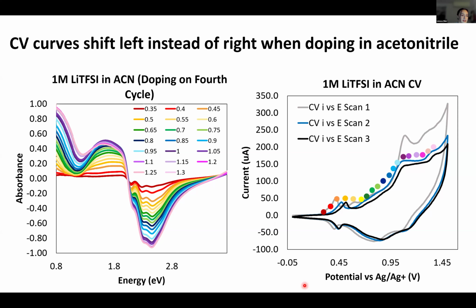And we hypothesize that this is due to regions getting irreversibly doped. They're not fully dedoped on the negative sweep. And so then the next cycles are doping the remaining undoped regions, which is getting harder and harder with each subsequent cycle. And swelling would make it easier to intercalate anions, which is why we don't see it shift left, because this solvent doesn't swell.